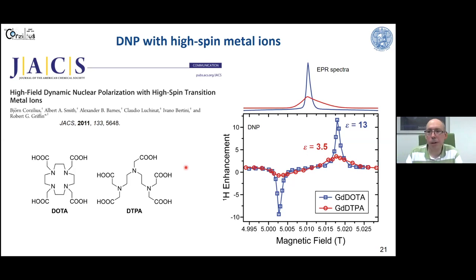And this was the introduction we made when we utilized gadolinium, first time at high field DNP. And here we could already see that we could achieve quite reasonable DNP enhancement factors of 13, which is probably nothing compared to 400 or something like that. You can get now with highly tailored bis-radical or bis-nitroxides. But for specialized applications, this is now opening a whole new market practically.